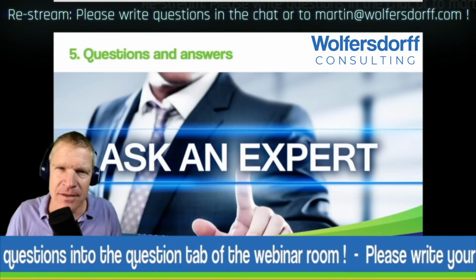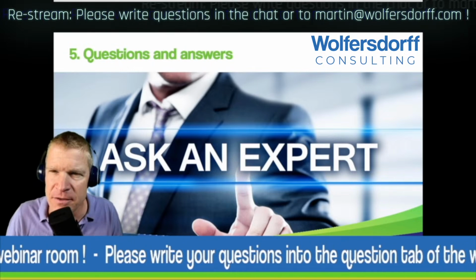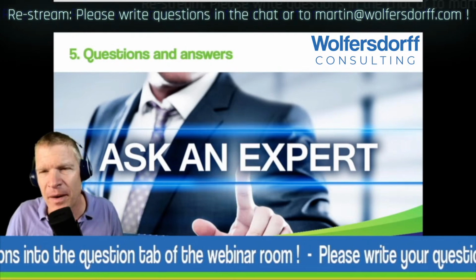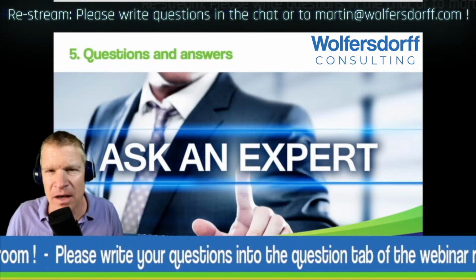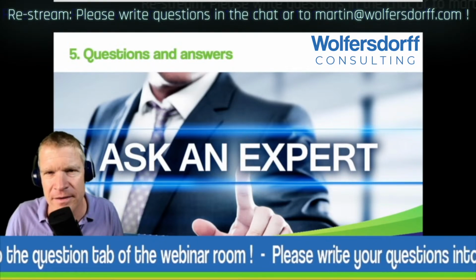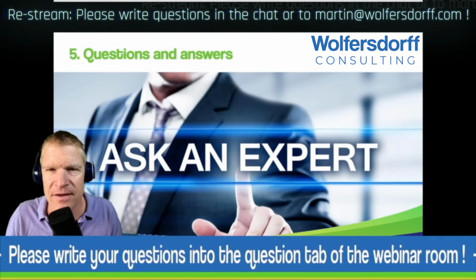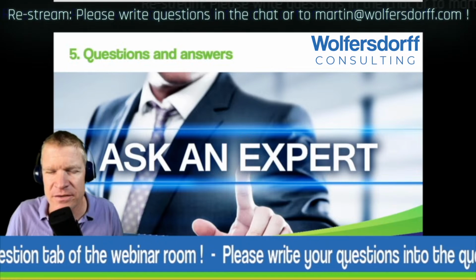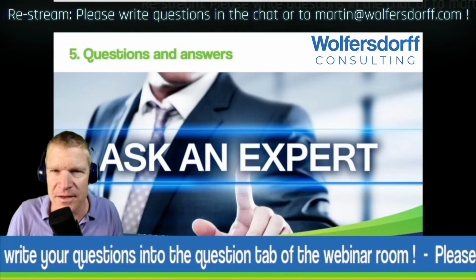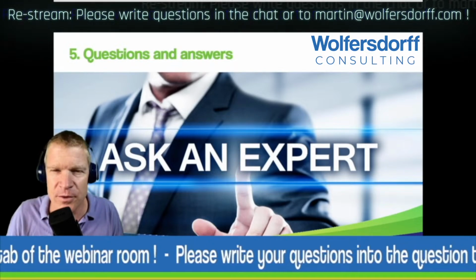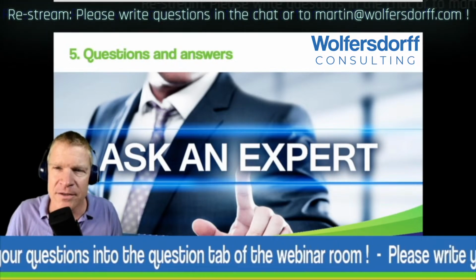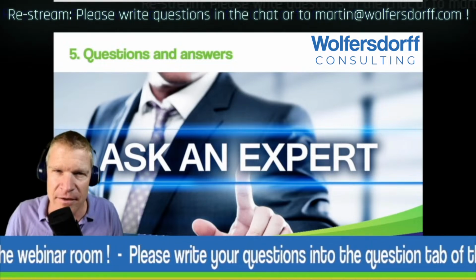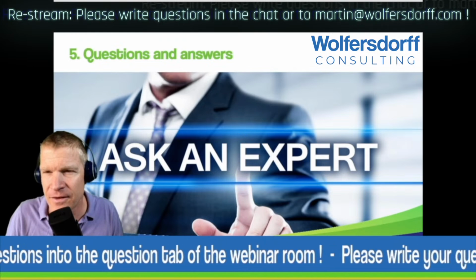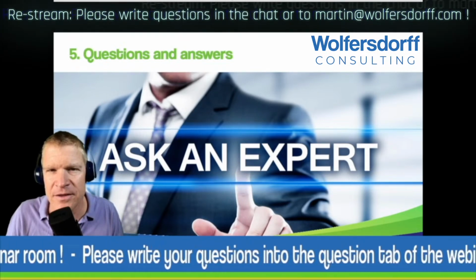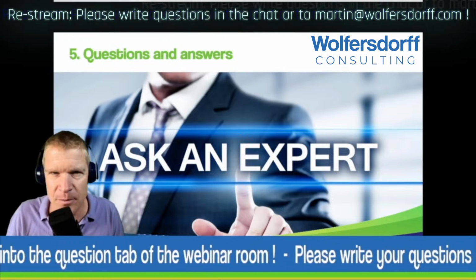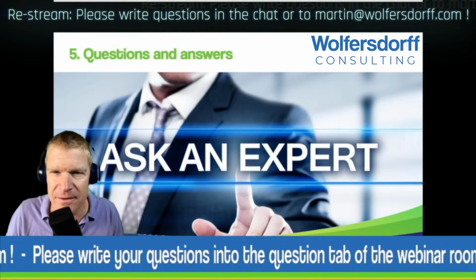Ravi from Capital Carbon: Martin, for pelletization, what is the best binder for plastic uses? So the binders used in carbon black tend to be molasses, so sugars, waste from the sugar industry, or lignosulfonates, added at a faint concentration, I think below 1%. I don't remember the exact percentage. I have heard of recovered carbon blacks that didn't need any binder for making pellets, that have really nice pellet and also pellet hardness without any binder. So I would say it depends, but the starting point would be molasses and lignosulfonates.